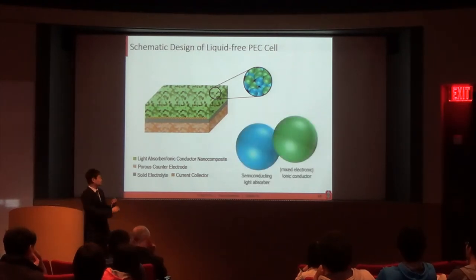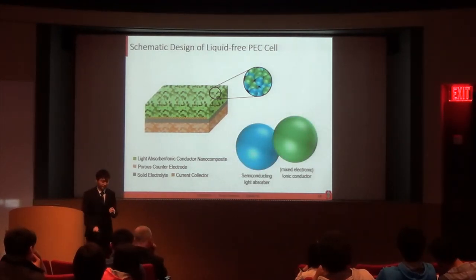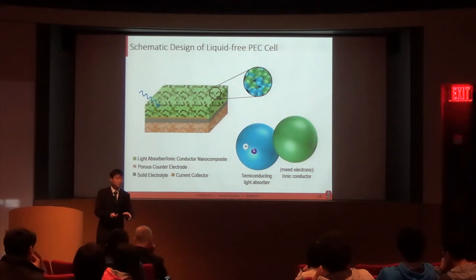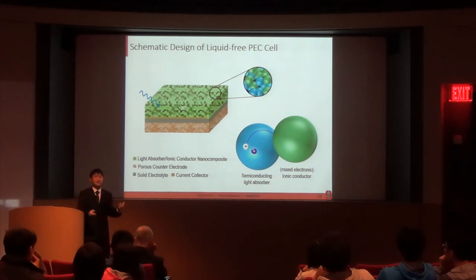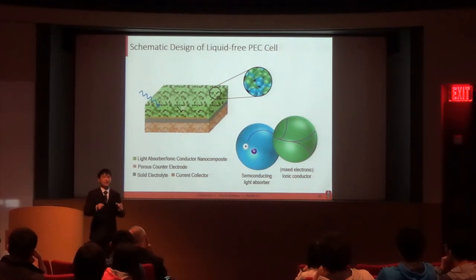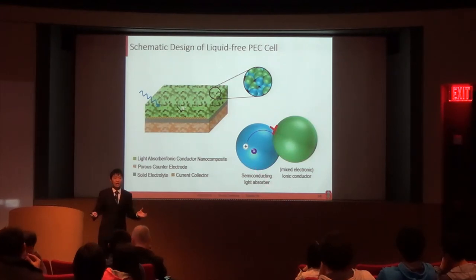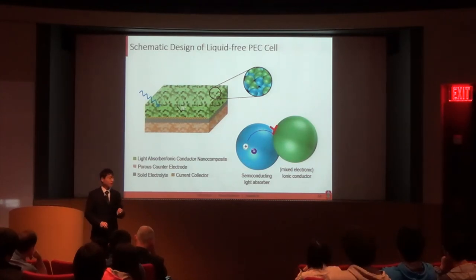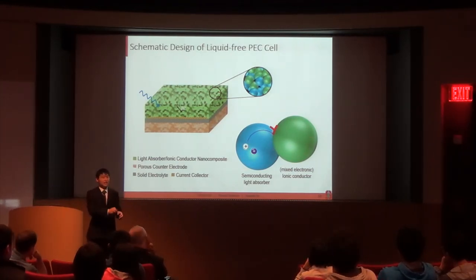So let me explain how this device works. Under illumination, the electron hole pairs will be generated inside a semiconducting light absorber as the hole migrates to the interface with the ionic conductor. There's a chance that it can jump into the valence band of this ionic conductor. So if this ionic conductor has some electronic conduction, which makes it a mixed ionic electronic conductor, the holes can further migrate for a longer distance. While in the case this ionic conductor has no electronic conduction, then the holes will be restricted within the vicinity of the triple phase boundary, where the electronic phase, the ionic phase, and the gas phase meet.